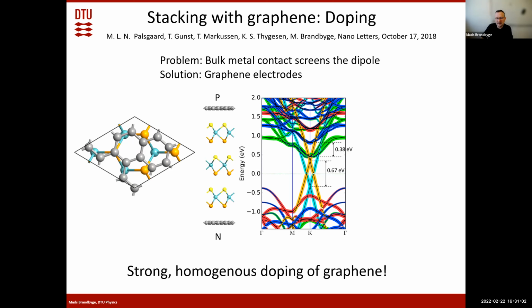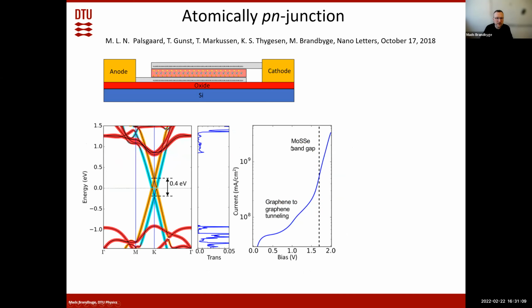Maybe it's difficult to make these stacks. As far as I know, it has not been done so far, but there's still hope. So here you see a device where we are doing calculations on just a single layer of this Janus structure, sandwiched between graphene electrodes. Here there's still a doping of the graphene. It's somewhat smaller than when we have three layers of the Janus structure, but it's still there. And what you see here is the IV characteristics, which show that it indeed behaves like an atom-thin diode. In the beginning, you have tunneling for low bias, and then when the bias gets approximately the band gap of the Janus material, you have a stronger increase in the current.